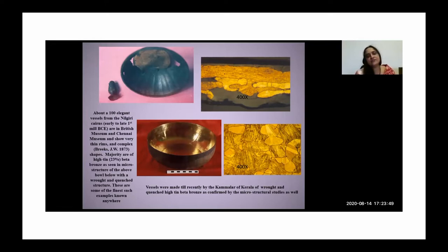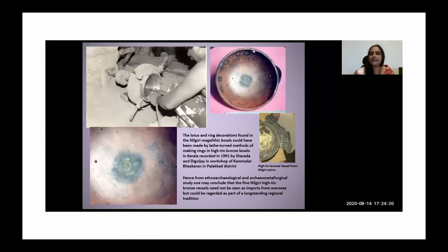Why that's interesting is that the structure of this vessel made in the Iron Age so many centuries ago is so very similar to this vessel, which is made more recently, where you're seeing this retention of the needle-like martensitic beta phase and some of the alpha plus beta, the alpha islands with the annealing twins and so on. So it shows that even in contemporary times, they were making these vessels by a similar process, both similar in composition and technique.